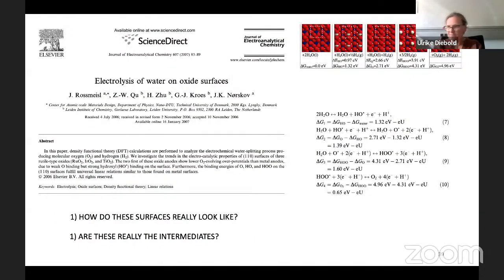And then, this is a very famous paper, right? Thousands of citations. Very nice, really, very famous, by Jan Rossmeisl and Jens Nørskov, where they looked at exactly these rutile 110 surfaces, like the RuO2 surface I showed you before, right? And then they looked at the electrolysis of water on these different oxide surfaces, so ruthenium oxide, iridium oxide, TiO2. They all have the same rutile structure, always the 110 surface that I showed you, the nice STM images before. And then what you do is you take the water molecule and you take the electron and the proton and you look at the change in G, and then you do it at a difference.